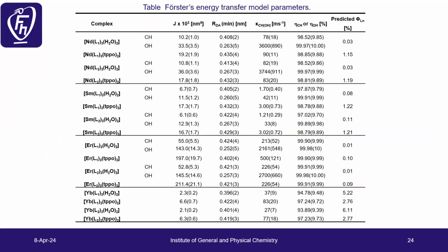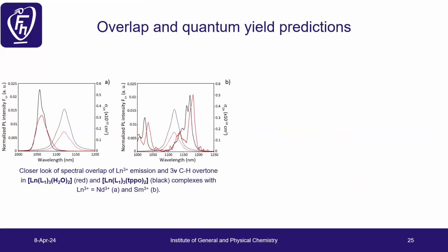With the quenching, here we can see the efficiency of CH, which is less compared to the OH groups in neodymium, same as in samarium. OH is 99.99%. So what we would ideally like is to have water-free complexes without any CH or OH groups, but that's quite difficult and quite expensive to obtain.